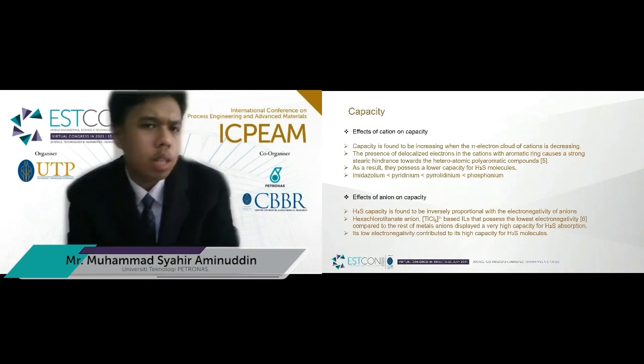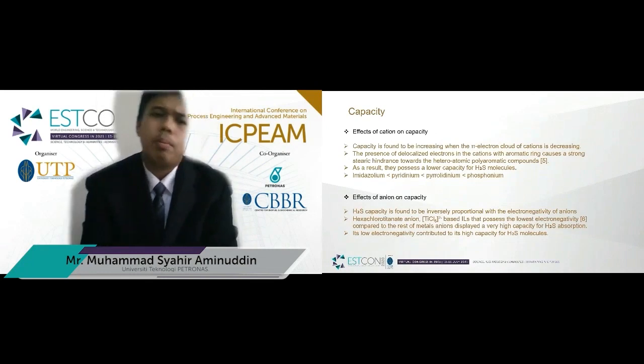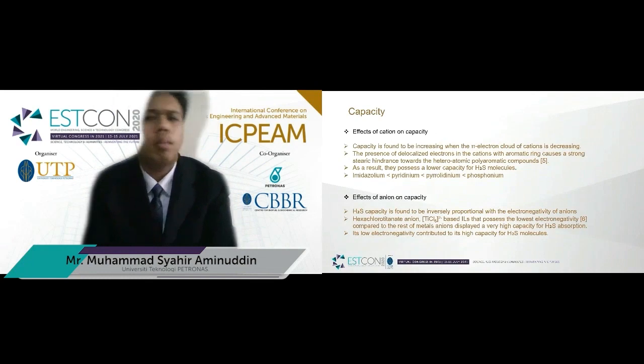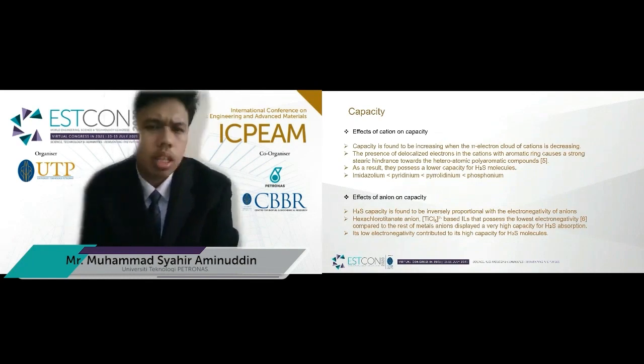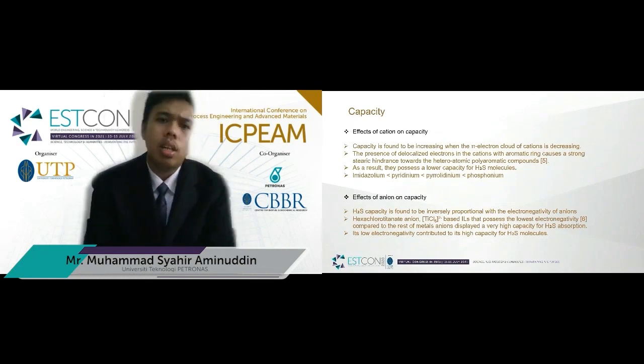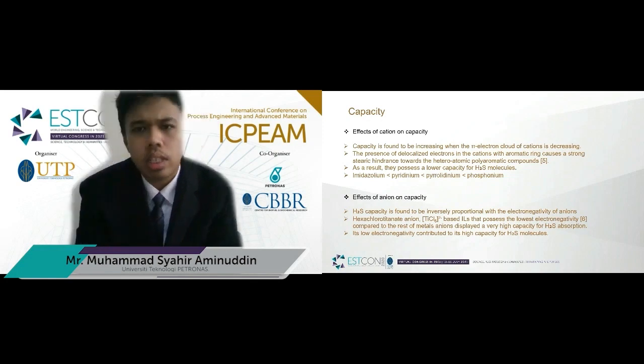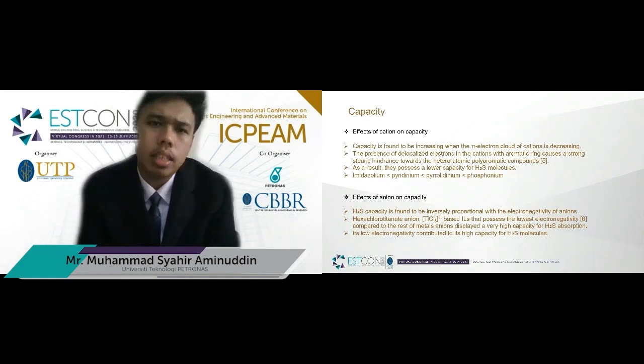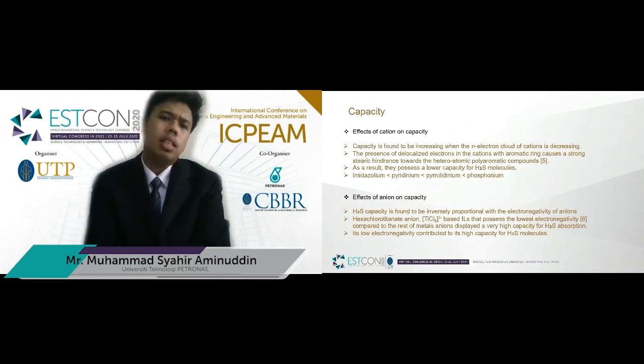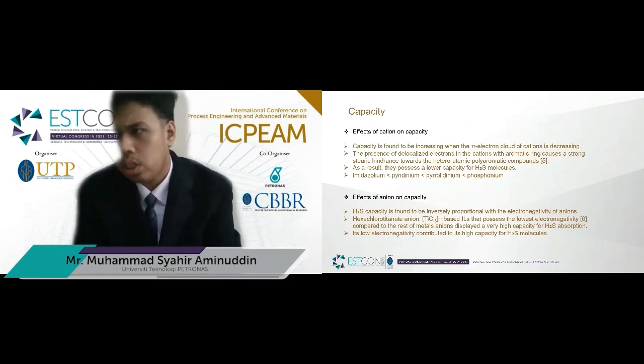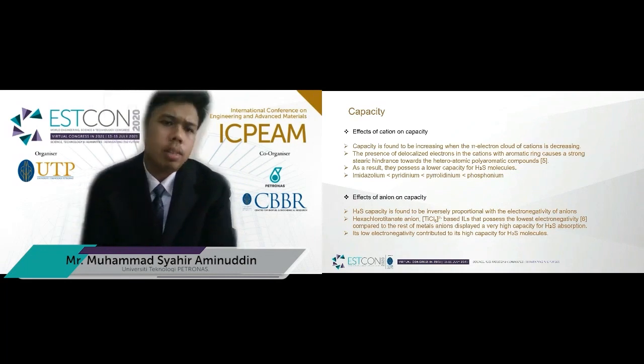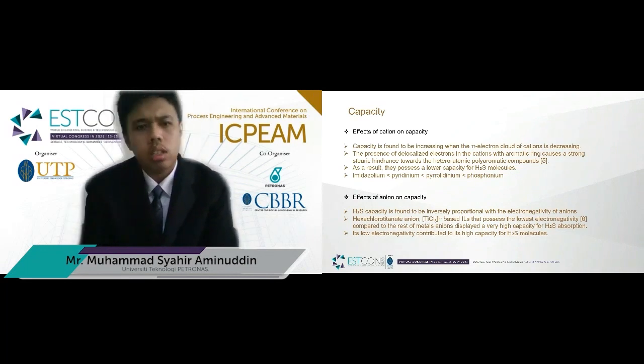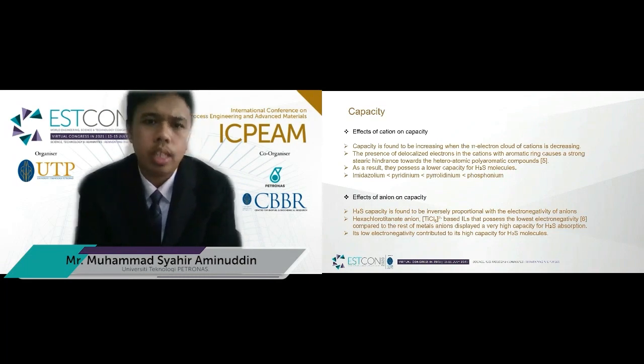Capacity is also affected by cations and anions, and capacity has been found to increase when the pi electron cloud of cations is decreasing. This is because the presence of pi electrons in the cations with aromatic rings causes a strong steric hindrance toward the heteroatomic polyaromatic compounds. As a result, they possess a lower capacity for hydrogen sulfide molecules. The capacity increases in the order of imidazolium, pyridinium, pyrrolidinium, and phosphonium.